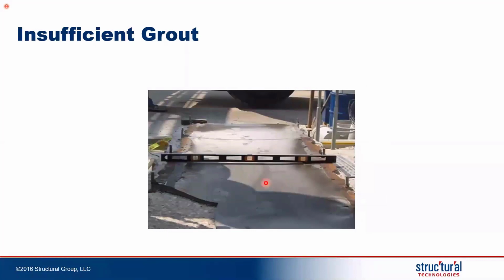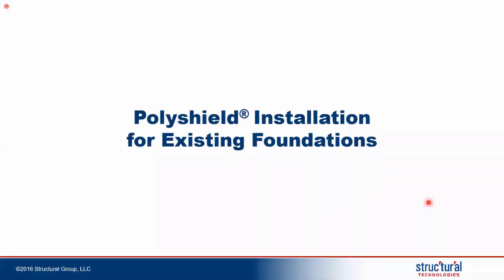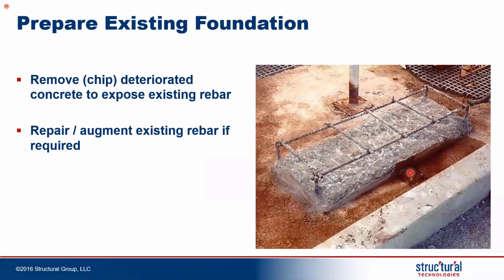Here's a photo of a base plate being removed due to vibration, and as you can see, there's not enough grout in the middle of the foundation, so the contractor did not pour enough grout to provide close to 100% contact with the base. So there's a concave surface there. So that's the conventional installation. So you can see there's a lot of steps, a lot of time, a lot of potential issues, a lot of guidelines to follow. PolyShield is very simple, and here's how PolyShields are installed for existing foundations.